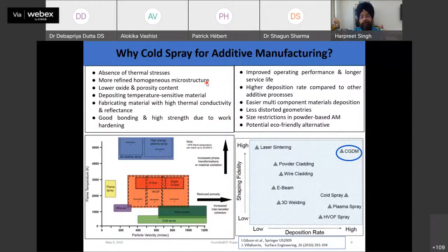So if you see a typical cold spray deposit, the microstructure will usually be refined when you compare it with the feedstock material, right? Low oxide content as well as porosity content. So this is another very strong point, that whenever you have temperature in your process, there is always a kind of risk that you are getting some kind of oxidation, because most of the material will oxidize as soon as you expose them to the temperatures.